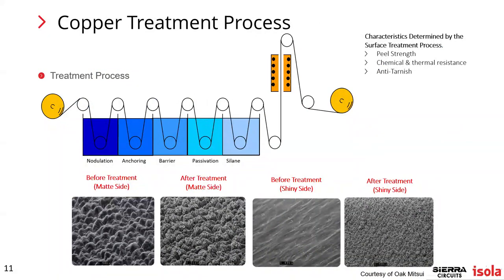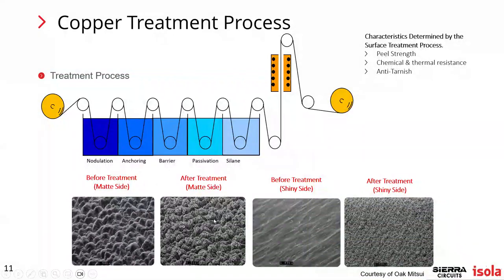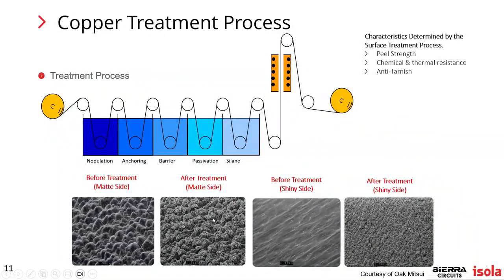In the treating process, they apply nodulation onto the material and then put an anchoring layer over the top to hold those nodules onto the surface. You can see the matte side — opposite the drum — and after nodulation and anchoring there are little tiny balls. If you're familiar with the cannonball method used in EDA tools, that's kind of where it comes from. However, in cross sections these nodules actually look more like stalagmites or pillars in a cave. You can also see the streaking from the polishing effect on the titanium drum, and the nodulation on the shiny side surface.